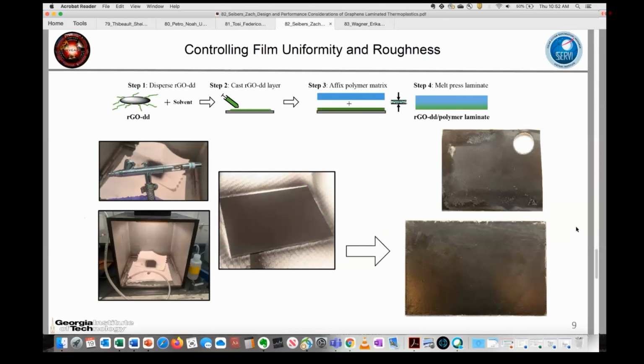So finally, what we're really trying to do is take this idea and look at surface roughness with more. We've come a long way in our processing, and we've got examples here of what a spray coated sample looks like, and you can see the old sample here. This is what I showed. I took the sample that was exposed to the lunar dust environment, it was this little hole. And you can see that this surface is irregular. It does have some issues. If you were to put a tape test on this, just stick some tape on it and peel it off, you would see graphene come off around the corners. We've gotten virtually rid of all of those kinds of problems. And we have fairly perfectly uniform samples, as much as you're going to get at this scale. This is about 2.5 inches by 5 or 6 inches in length.